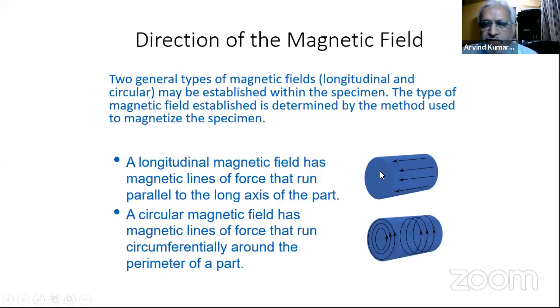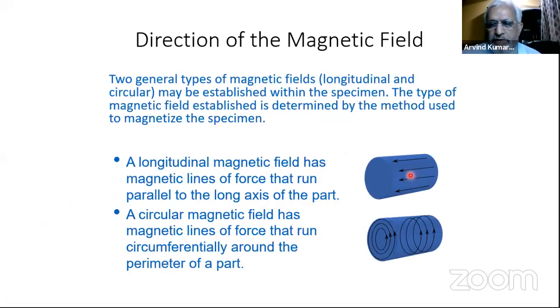Now, as you see, this is a longitudinal field, I would say, and this is a circular field. If you have a defect which is parallel to this line, then it's not going to be detected. Even if it is up to 45 degrees to these lines, it would still form an indication. But if it is less than 45 degrees, tending towards parallel to these lines, it will not form an indication. Here it is the other way. A longitudinal defect you will be able to see, but a circular defect you will not be able to see because it runs parallel to the magnetic flux. So you should know which kind of method will generate what kind of field.